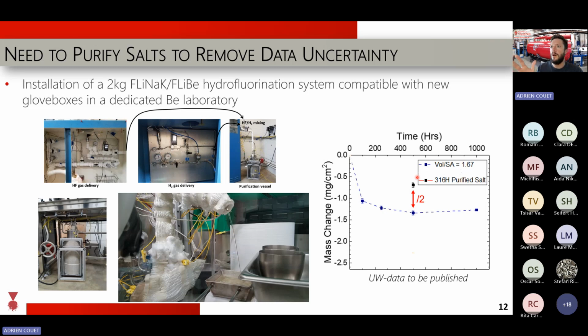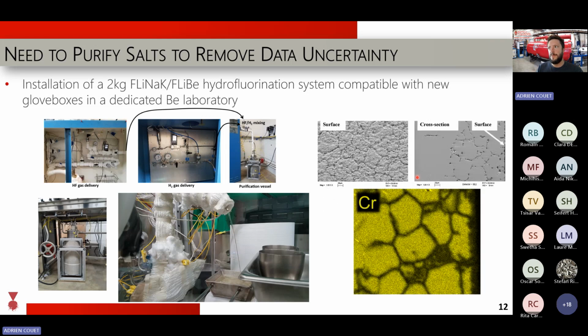The main, as we found out, and I don't have the data here, the main impurity that is driving corrosion in this case are oxygen-bearing impurities, mostly moisture that could create, for instance, HF in your salt, which is one of the responsible. So how does that look?